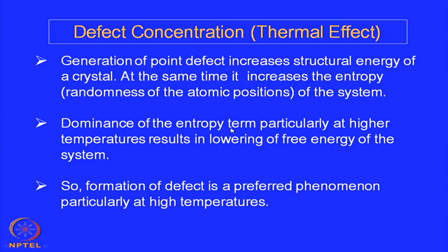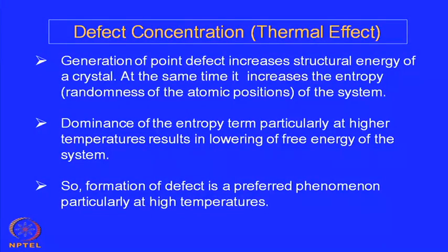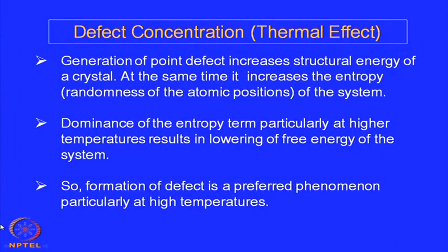So, it is not that defects are not allowed, defects are actually preferred, because by generating this kind of point defects you reduce the free energy of the system. Because the entropy term increases, and by increasing the entropy term you actually reduce the free energy, and therefore defects will automatically form at high temperature. Depending on the temperature, defects are automatically going to come, and it is a preferred thing from the thermodynamic point of view.